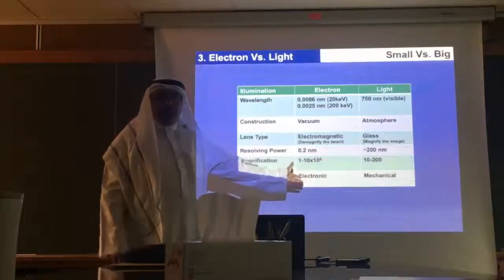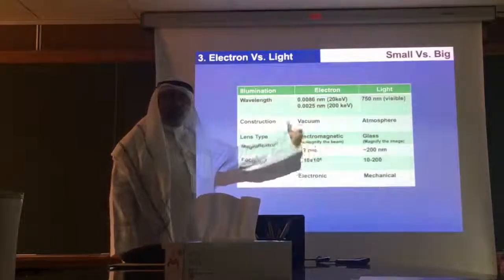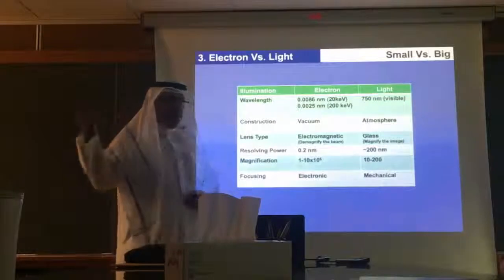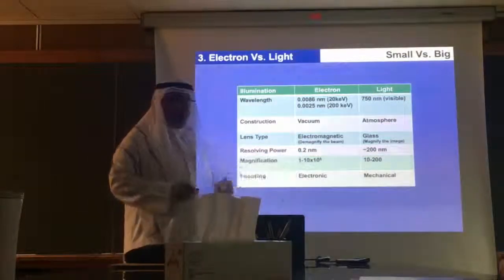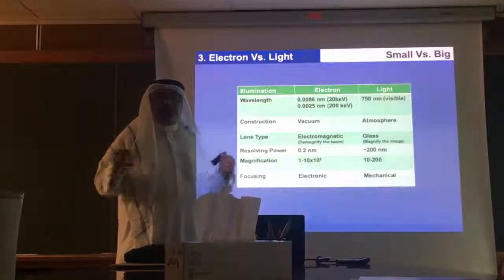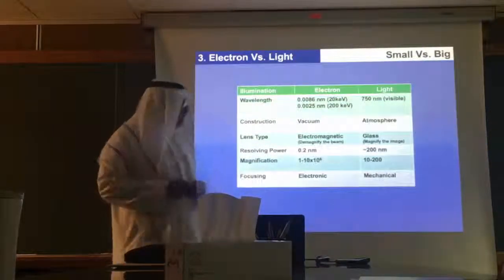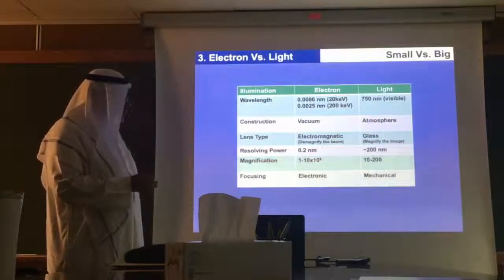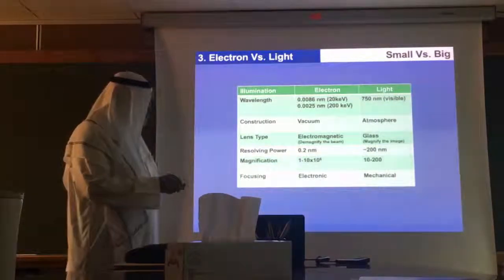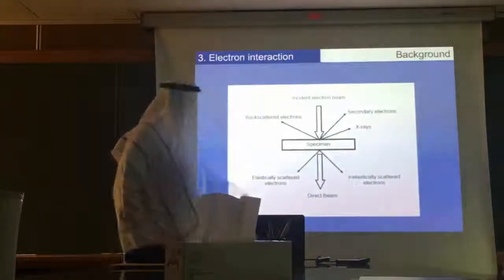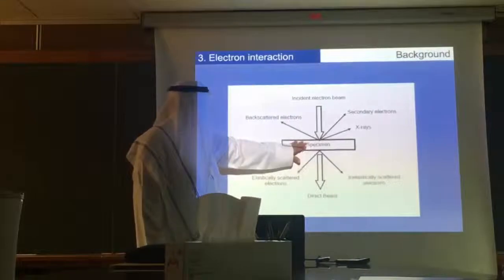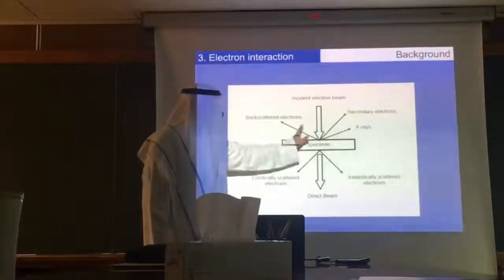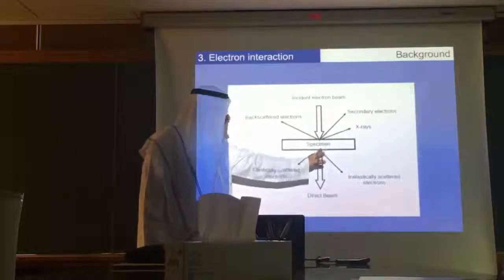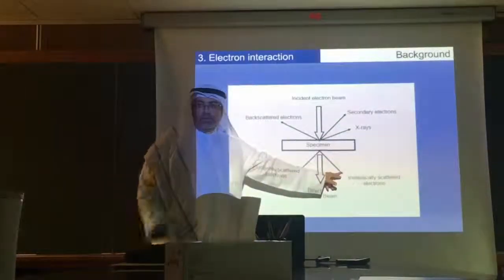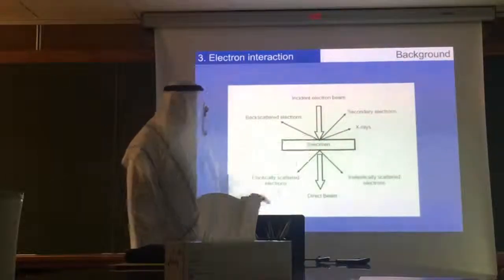The resolution can go up to 0.2 nanometer or even smaller than that. There are some devices now that can go to 0.1, and last time there was a seminar in the electron microscope unit. One of the companies said we can reach the pico resolution. So very, very, very small resolution. The magnification can go to a million times here, and the focusing, of course, this is mechanical and this is electronic. So when you have your nanomaterial in the middle, if you hit it with the electron beam, there is some signal bouncing back from the sample, and there is some signal going through the sample, if my sample is very thin.